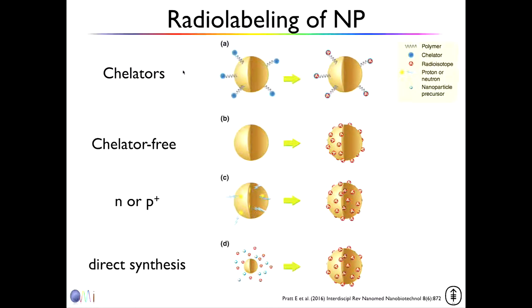So one is the most commonly used, which is you just put a chelator on your nanoparticle, and then you add your radiotracer to it, and then it's on. And that's the question that was asked before: do we really know whether it is on or not, or are these guys detaching? Are they dechelating? Are they transchelating? Is the tracer lost and we're looking at an empty tracer without the nanoparticle, which secretly, MI6-wise, is already somewhere totally different than you actually think it is.